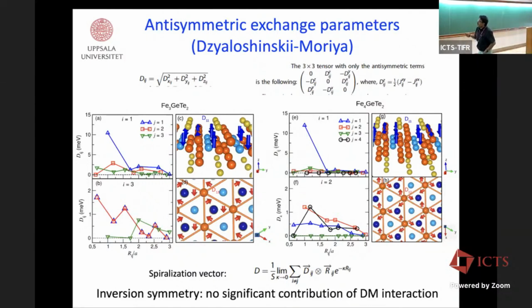Sometimes you see that there are non-zero values of these Dzyaloshinskii-Moriya interaction parameters. You only expect non-zero values when inversion symmetry is broken. Locally, between a pair of magnetic moments, inversion symmetry is broken. That's why you get a non-zero value of Dij. But when you add them globally, we have seen that they cancel each other. Specifically, this D11, you see these up and down arrows. These are all vectors. If you sum them up, they give you zero contribution to the DMI effect. Overall DMI effect is zero.